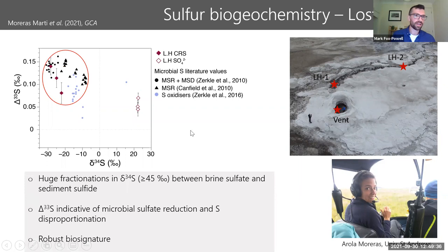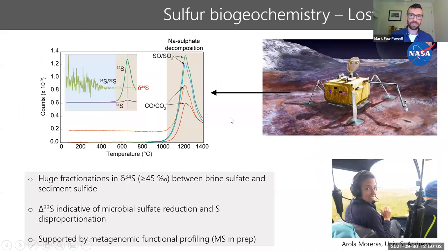But also by using these minor isotopes, we can start to pick apart some of the sulfur cycling metabolisms like sulfide oxidation and sulfur disproportionation. So these are microbial metabolisms that cycle sulfur. And by using this quad sulfur isotope approach, we can start picking apart this surface record of subsurface processes. And now we're building that into using spacecraft relevant instrumentation, in this case ramped pyrolysis mass spectrometry of the sort that may one day fly on the Europa lander spacecraft, to try and recover some of these sulfur isotope signatures using mission relevant techniques. That's ongoing work at the moment, working with Amy McAdam at NASA Goddard and their team.